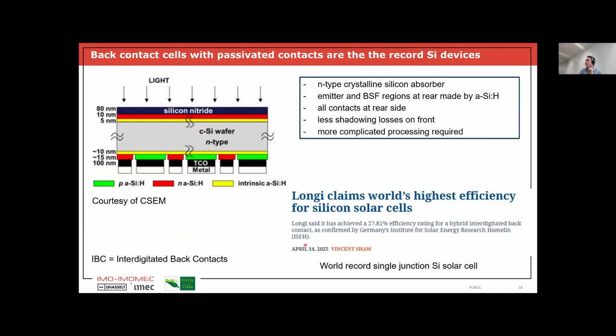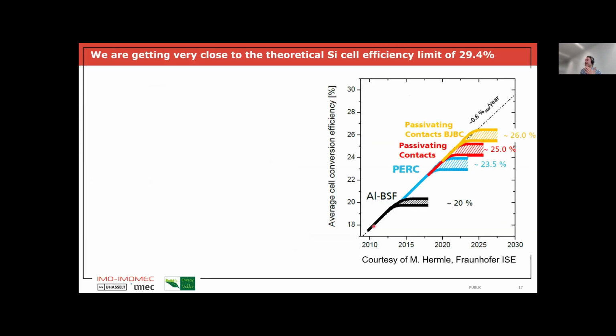And actually, quite recently, a couple of weeks ago, a new world record silicon solar cell efficiency has been achieved with this type of structure. And the efficiency, the new world record, is now 27.8%. So that is the highest efficiency that has ever been reached by a single junction silicon solar cell. The previous record was something like 27.4. So this is very high efficiency because theoretically, the maximum efficiency that we can get with a single junction silicon solar cell is 29.4. So this is the best we can ever do. And with 27.8, we are getting quite close to that.